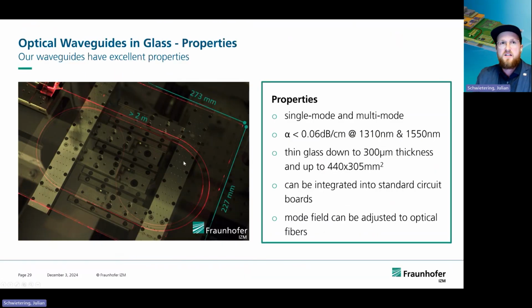And these waveguides have really excellent properties. So we can make them single mode and multi-mode, depending on the parameters for ion exchange. They have really low propagation loss of 0.06 dB per centimeter at our telecommunication wavelengths, but they're also transparent for visible light. And we can make them into glass up to a size of 440 by 305. And we are upscaling this process at the moment to the large 515 by 515 panel size.